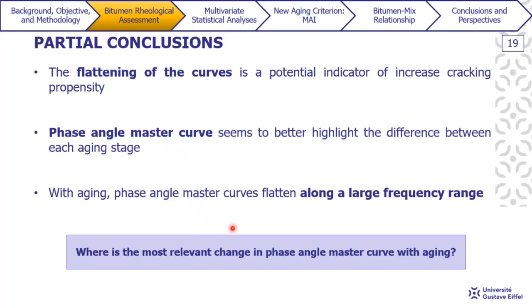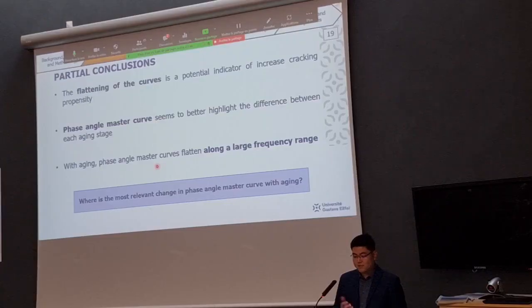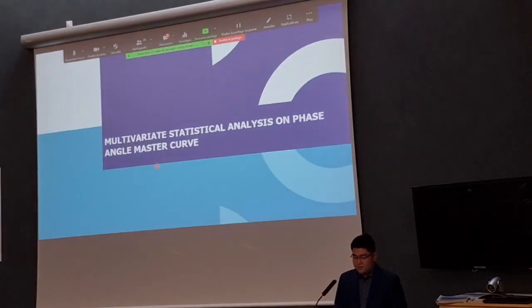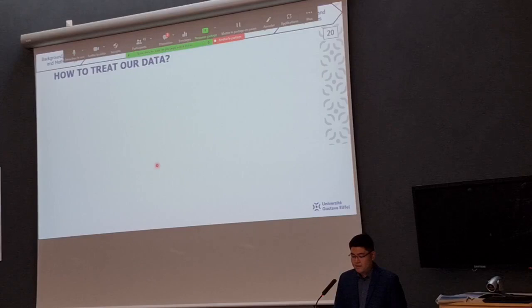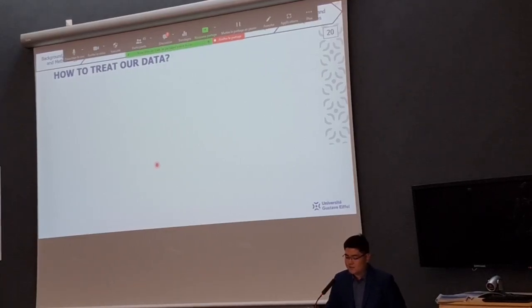In this case, the phase angle master curve flattens along a very large frequency scale, which is unlike the modulus, where we only see an increase at the reduced frequencies. So the question is, where is the most relevant change in the phase angle master curve with aging? To address this question, we decided to use multivariate statistical analysis on the phase angle master curve, because our first question was how to treat the phase angle master curve.